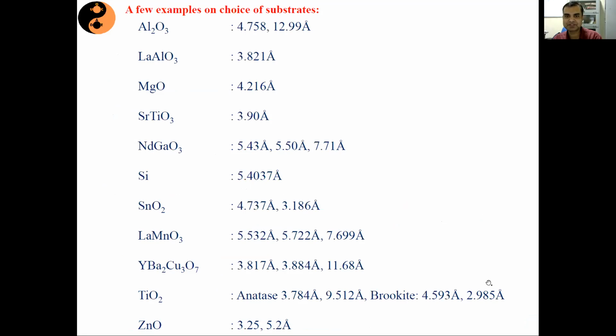Now, how do we choose substrate? Suppose if I have to make an epitaxial film, epitaxial films, when the film retains similar crystalline arrangement as that of the substrate. So suppose if I have to make a film of say LaMnO3 5.53, then the easiest substrate that I can think of is NdGaO3, right? Now the question arises, can I use this LaAlO3? The answer is yes. If you look at this LaAlO3, make a square, then the diagonal will be close to 5.4. So that means the lattice parameter matches very close to that of the film lattice parameter, and therefore that kind of substrate can also be used.